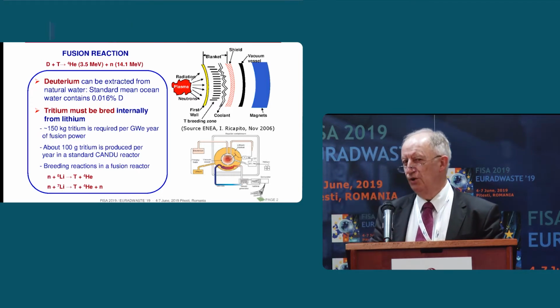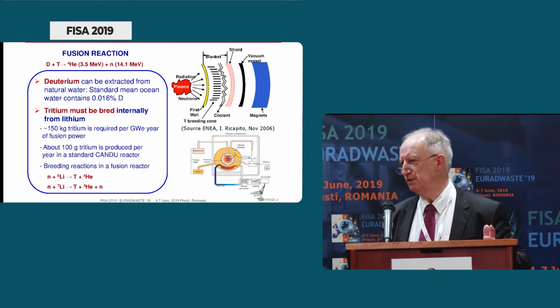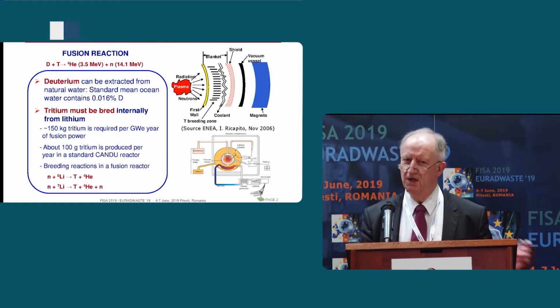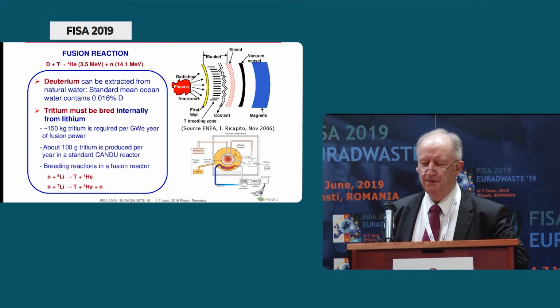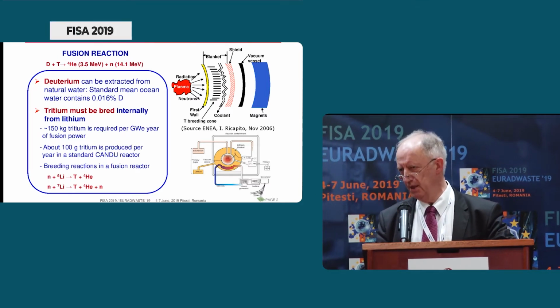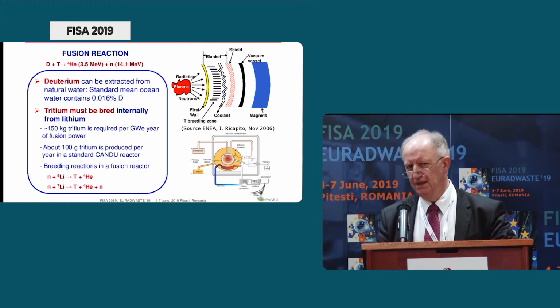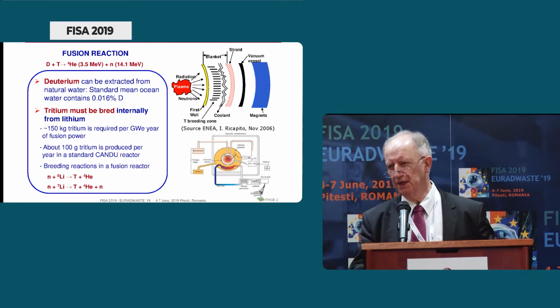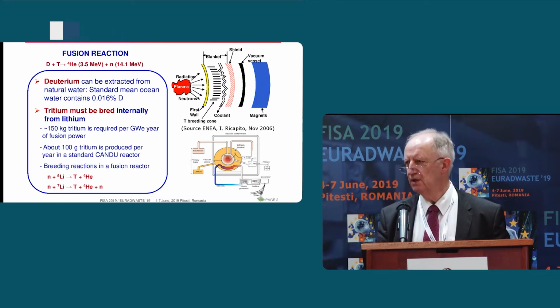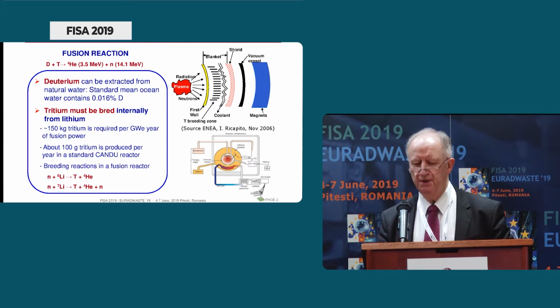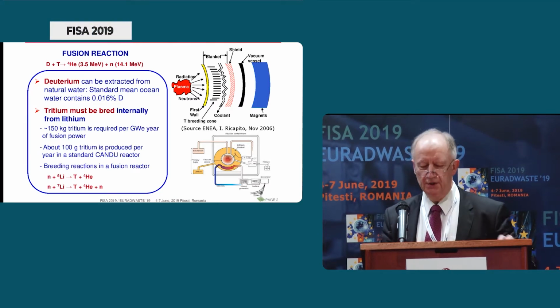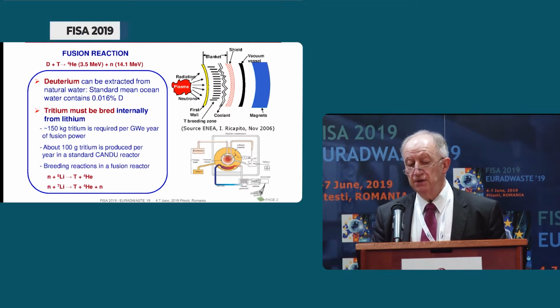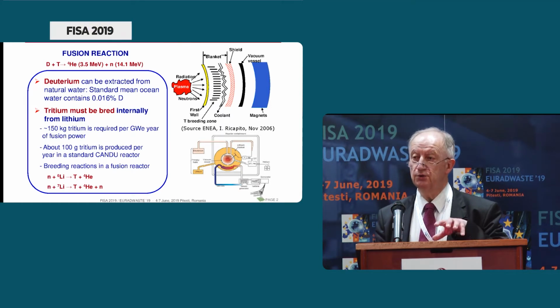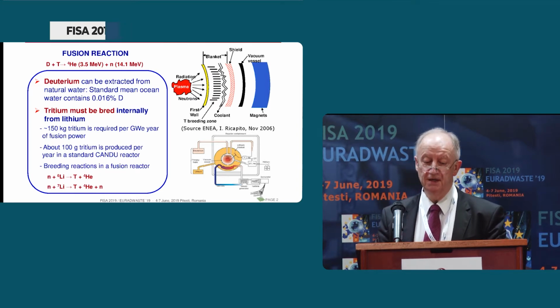It would be mission impossible also considering that the coverage of the plasma is at most 80% because of all the devices, diagnostics and vacuum pumping that are needed. Therefore the magic is to possibly use neutron multipliers like beryllium or lead that can multiply the neutron through n,2n reactions. Those are threshold reactions, but the 14 MeV neutron has a sufficiently high energy to multiply the neutron, and from one 14 MeV neutron get about 1.5, maybe lower energy neutrons. So there are 2 missions for this neutron within the blanket: to generate power, to generate electricity, and also to regenerate the tritium by ultimate capture on the lithiated atom.